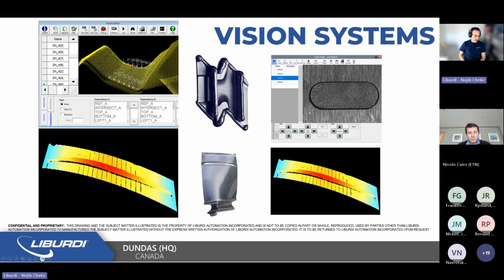In this case, we could use just a visual solution, so a top camera that can generate a black and white type of image of the area of interest. And by using the contrasts that are generated in this image, you can generate sites of interest. Here, they're very small, but those would be sites of interest that were calibrated with regards to the position of your torch tip. And then by transferring those site positions to the robot, then you can generate the tool path of interest and generate the repair or manufacturing again of a new component using this technology.